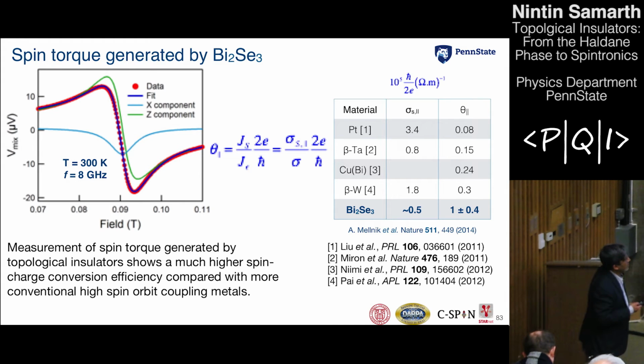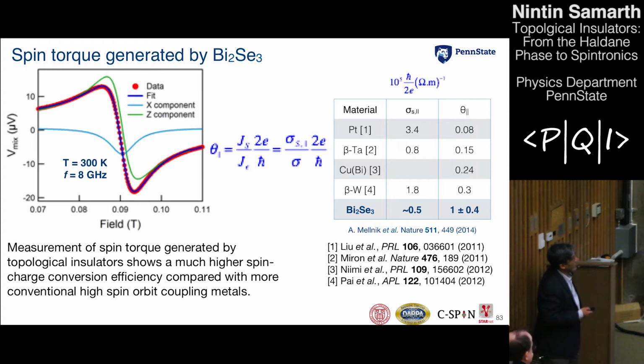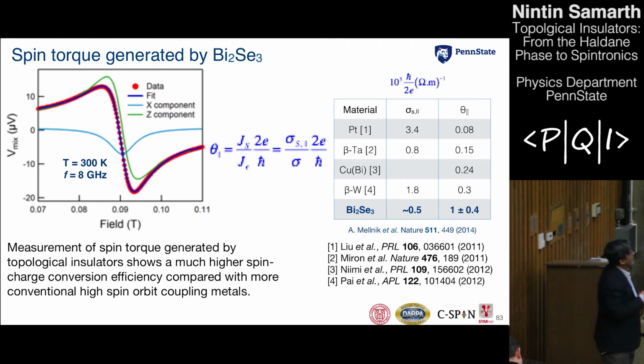So the bottom line is that if you plot this parameter, here in the table is this efficiency theta parallel given for different kinds of metallic systems, and then for bismuth selenide, you find that the efficiency that we get for this process in bismuth selenide is quite a bit higher than what you see in metallic systems. Now there's a word of caution over here, and the word of caution is that in this bilayer, remember